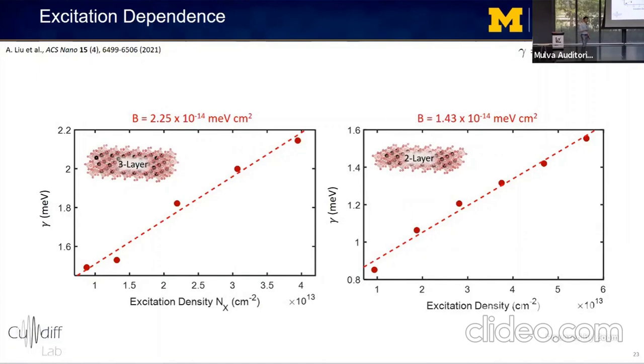And we also performed measurements as a function of excitation density. And to account for differences in optical absorption, we converted the excitation fluence to excitons per square centimeter as the x-axis. And the fitted broadening parameter B, which is the slope of these linear fits, we also find to be smaller for the thinner 2-layer nanoplatelets, which indicates that they're also more robust against excitation-induced dephasing.